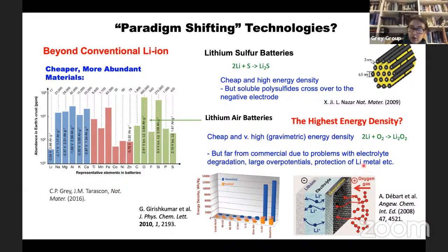The thing that we work on a lot in my group is the lithium oxygen battery. This is the only technology that has the same energy density of gasoline or petrol. If we could get that to work, it really would be a game changer. This is something where you react lithium plus oxygen to form lithium peroxide. You go via oxygen, via superoxide to peroxide, in the same way that you would in a fuel cell. So you have a carbon electrode that supplies the electrons, the oxygen comes in, and on the surface of these carbon forms, you form the peroxide.